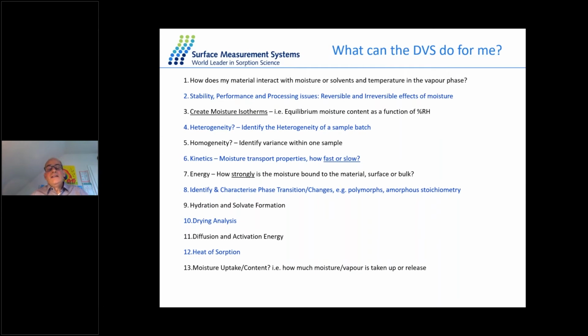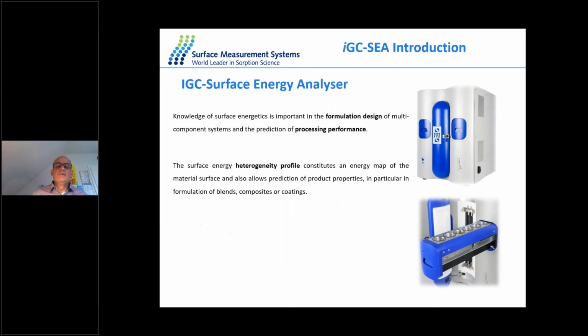You can identify phase transition, glass transition, recrystallization, polymorphism as a function of humidity or other vapor pressure and temperature. And that's, I would say, a big difference to DSC, for example, where the humidity is constant. Hydration and solvate formation, drying analysis, diffusion and activation energy, that has to do, of course, with kinetics, the heat of absorption, and of course, last but not least, I think you do all that, measure moisture uptake and content: what amount of vapor is taken up and released.